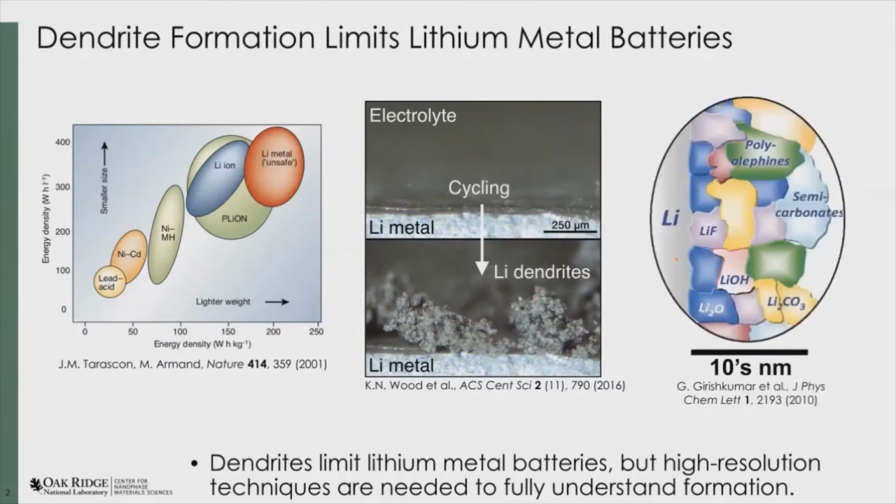And these are tied intimately to breakdown of the electrolyte on the surface of the lithium. So the electrolyte breaks down and forms these solid and kind of soft materials at the interface here. And you can see that it's thought to be on the order of tens of nanometers in size, or maybe even smaller, but it has a lot of small components inside. So we're talking about nanoscale things here. And the inhomogeneity here is thought to be able to seed the dendrite growth. And so understanding this structure and chemistry at this nanoscale at the interface is very important for stopping these dendrites